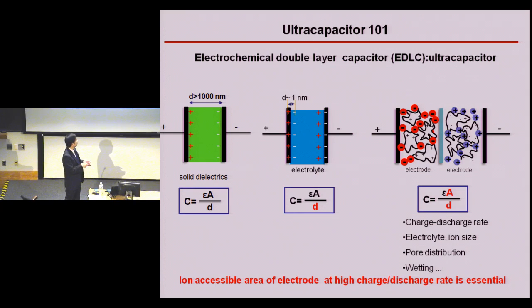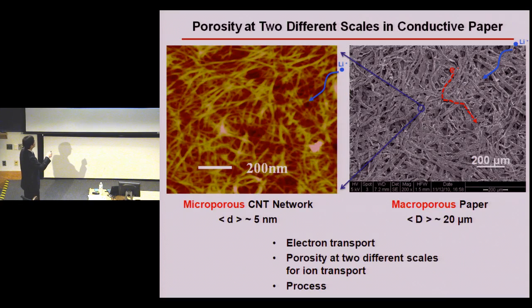But now the problem comes. Is this surface area accessible to the electrolyte, especially for a supercapacitor, because everything is moving so fast? Even though you may have a high surface area, this surface area may not be accessible. So this comes to the beauty of this conductive paper for supercapacitors. In this case, we have porosity at two different scales. We have fibers with 20 micron diameter. On top of it, we have a nanotube coating with diameters of about 5 nanometers. So that means we're talking about porosity at two different scales. And in this case, the paper is so conductive that you can move electrons on the plane of the paper.